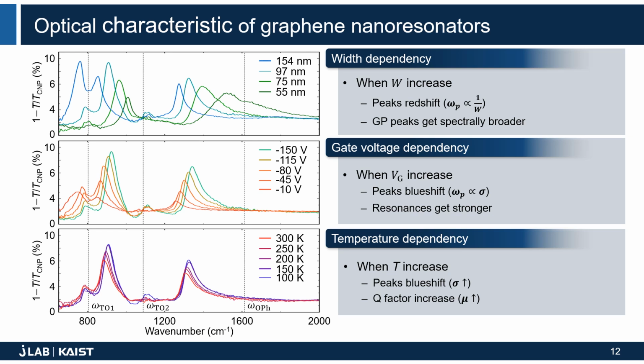We can see multiple resonance peaks in the normalized extinction spectra. The left peaks are due to hybridization between graphene plasmons and surface phonon modes of silica. Such a hybridized mode is called surface plasmon phonon polariton. The top two figures illustrate how the normalized extinction spectra depend on the resonator width and carrier density. Both peaks blue shift as width decreases and carrier density increases.